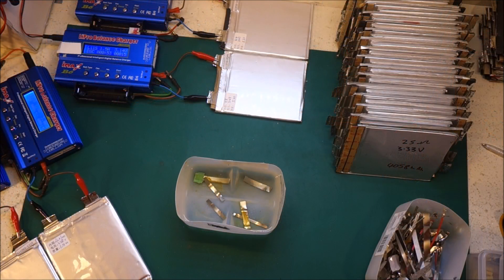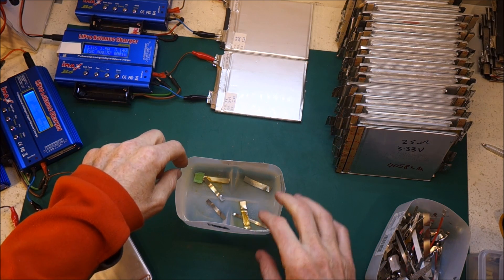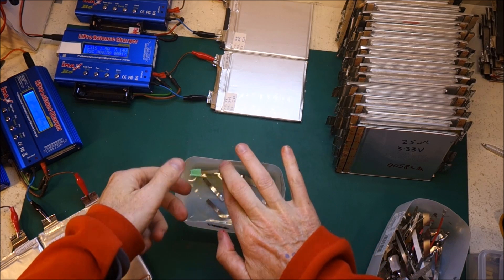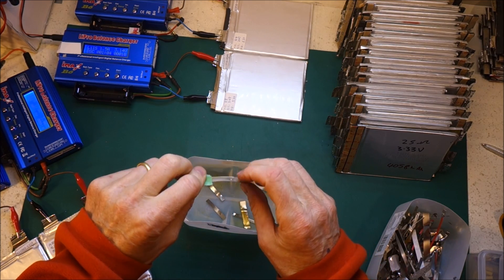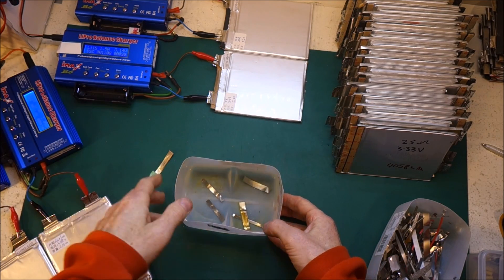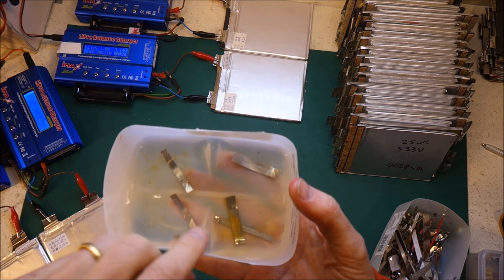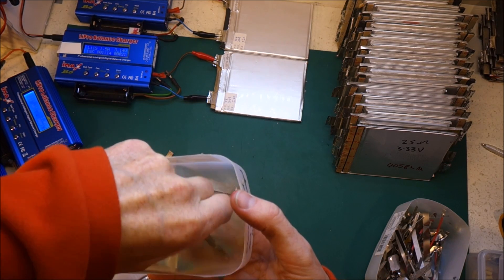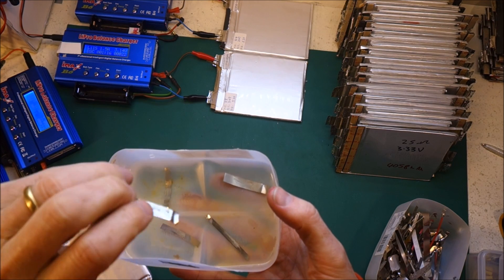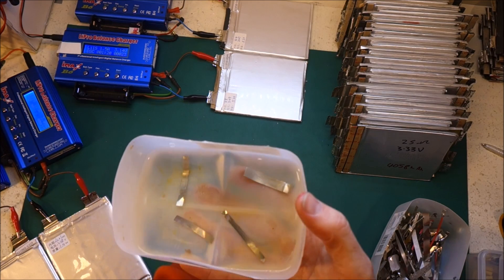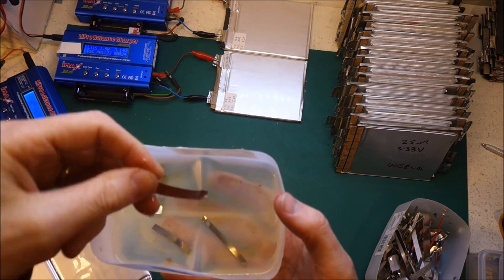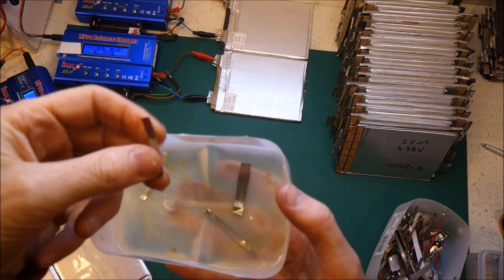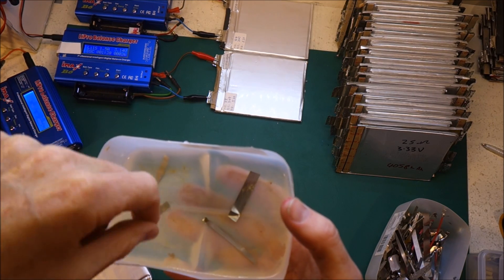Well, here we are 18 hours later and it's pretty clear that once again there's a bit of rust on my strapping. If we have a closer look, one of them definitely has rust on it. So that's off a random laptop battery. And then these ones are absolutely fine.